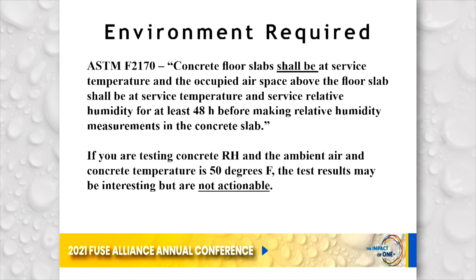ASTM F2170 states concrete floor slabs and the occupied airspace above the floor slab shall be at service temperature and service relative humidity for at least 48 hours before making relative humidity measurements in the concrete slab. So if you're testing concrete relative humidity and the ambient air and the concrete temperature is 50 degrees, that test result may be interesting, but it's not actionable.